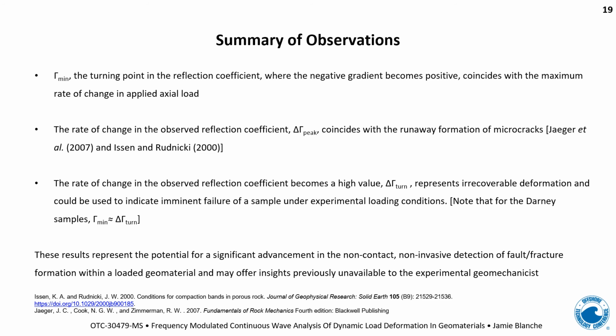Secondly, the rate of change in the observed reflection coefficient, the changing gamma peak, coincides approximately with the runaway formation of microcracks, and that's in keeping with the theories put forth by Jaeger et al. 2007 and Issen and Rudnicki in 2000. So, thirdly, the rate of change in the observed reflection coefficient becomes a high value, or in other words, where the rate of change of gamma has a turning point, represents that irrecoverable deformation and could be used to indicate imminent failure of a sample when it's under experimental loading conditions.